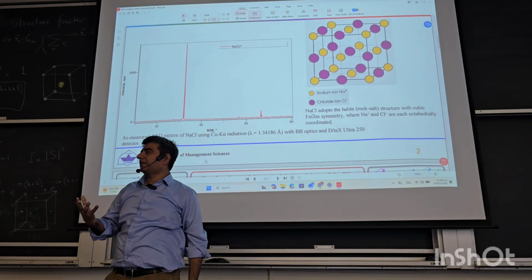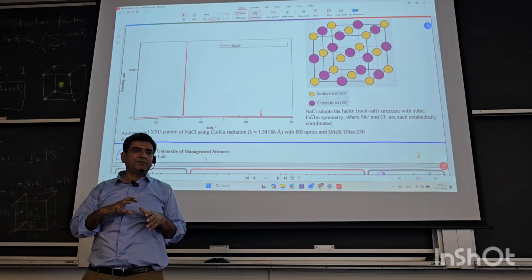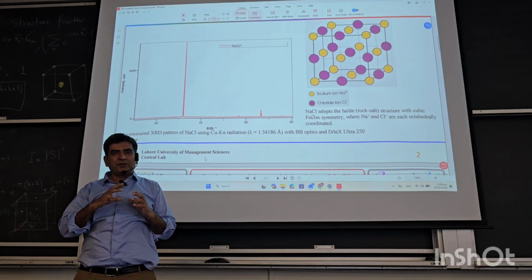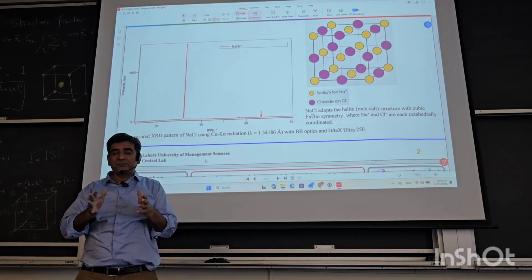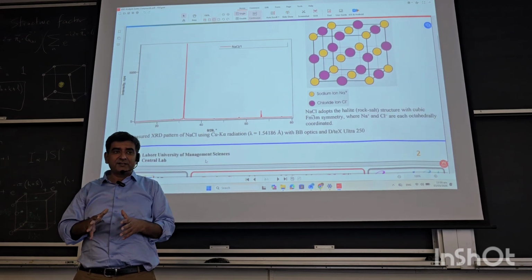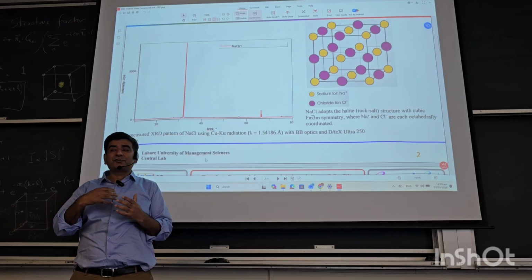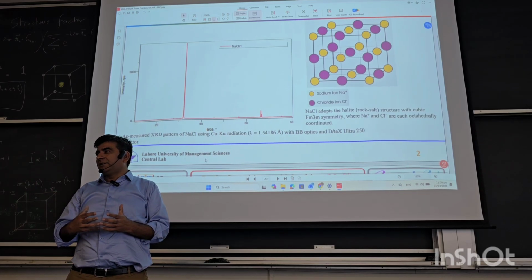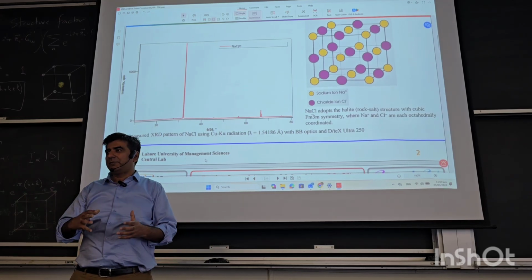But there are other factors which contribute to the dependence of the intensity on angle. There could be polarization effects, there could be thermal effects which give rise to broadening of the peaks, there could be strain inside the system, there could be other effects such as the Compton effect also happening, there could be secondary absorptions and reflections taking place. So it's a very complicated process.